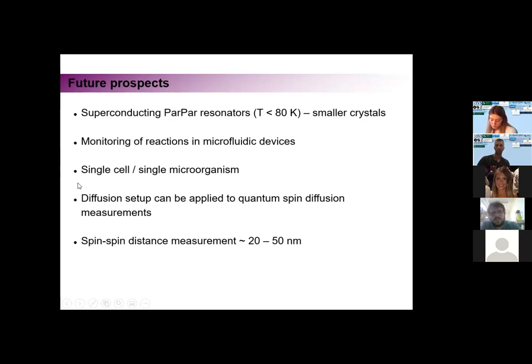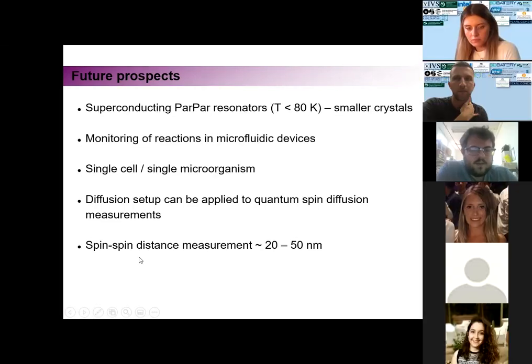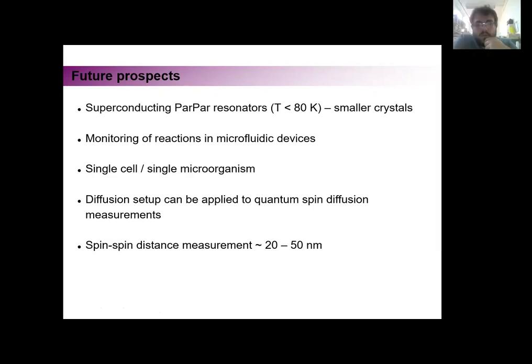Okay, and what I showed you with the diffusion setup, there we measure the actual real diffusion of the liquid. And if we freeze our samples, we can also measure the quantum spin diffusion, which is the diffusion of the spins, how they are moving through space. And from this, we can use it to make a measurement of the spin-spin distance, like I showed you in the beginning, on biological molecules, if the distance between two spins is 20 to 50 nanometers.